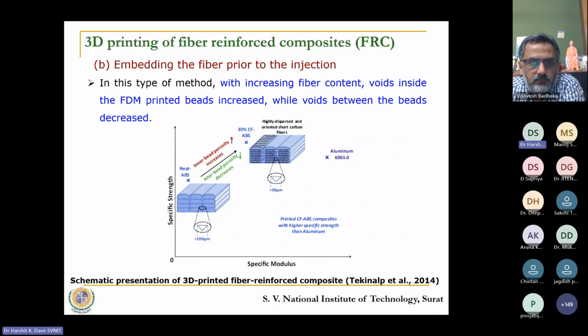The process results in very good parts largely because of the presence of fibers. This particular one is an observation wherein carbon fiber is mixed with ABS in 30% proportion. So when chopped carbon fibers are mixed in the proportion of 30% in ABS, we observe that the strength of the part drastically increases.